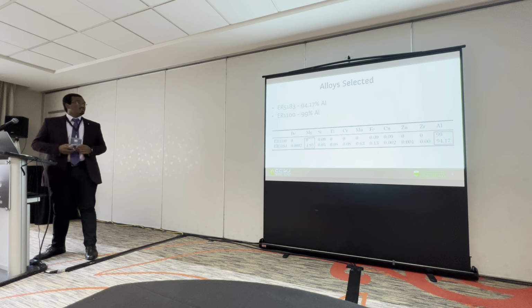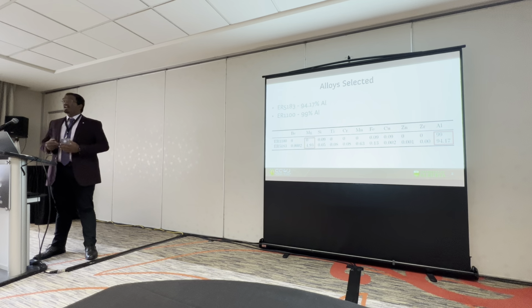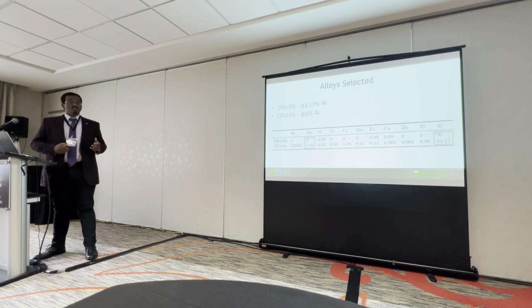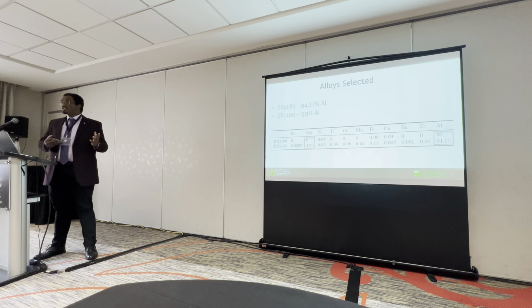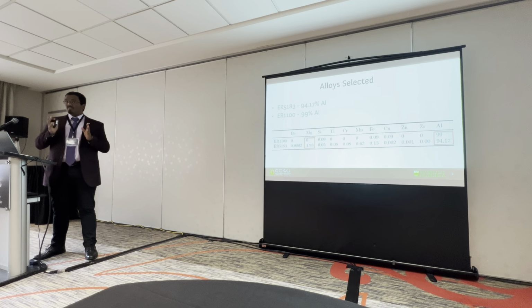For this process, we select two alloys, 1100 and 5183. I chose these two alloys in particular because 1100 has 99% aluminum and 5183 has 94.17%, but the remaining 5% is made up with magnesium. These two alloys were selected because this will give us a good understanding of the effect of magnesium.